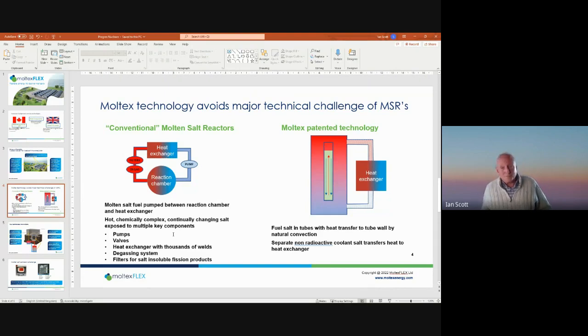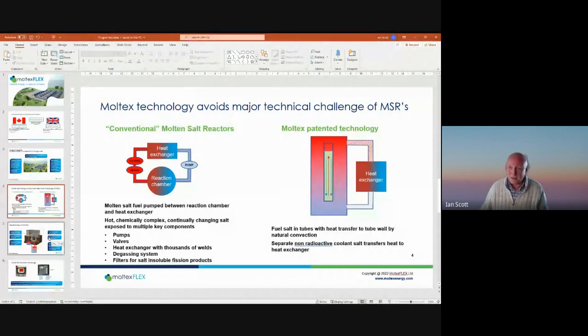The Moltex approach is different. We put molten salt fuel in tubes, pretty much like in most current conventional reactors. Instead of uranium oxide, we put molten salt in the tubes. That keeps the fuel isolated in tubes without any moving parts present at all. Heat circulates within the tube by natural convection, and it's taken away from the core by a second non-radioactive molten salt, which takes it to a heat exchanger to do useful work. That is the core technology. It is radically simpler than the pumped systems.